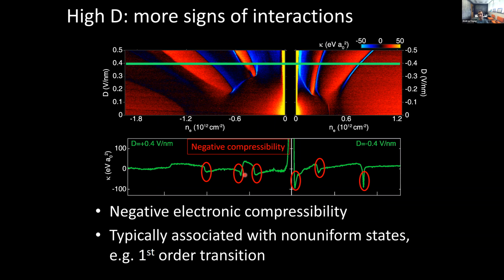And that's not something you can get from a single particle picture. It's typically associated with deviations from uniformity in your 2-dimensional electron system. But maybe the most obvious explanation, and what turns out to be the case here, is that these are associated with first order quantum phase transitions tuned by the density, where, as I'll show you, you're going from states of one type of symmetry to a different type of symmetry.